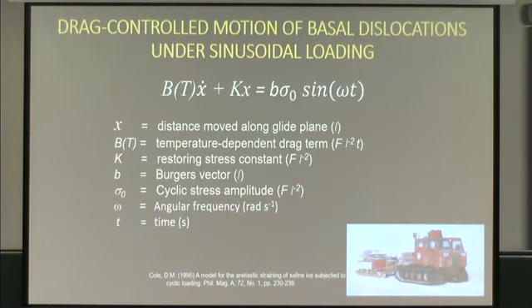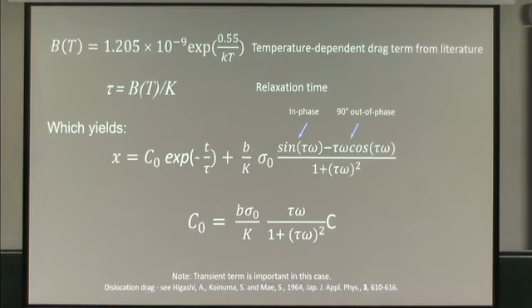So here's the physical basis for the model. You have a dislocation that's sitting at position X. Its response to a cyclic load is drag controlled. In other words, there's a temperature dependent drag that inhibits it as a function of its velocity. And there's also a microstructural stress that is acting on it as a function of its position. Physical quantities described here, nothing arbitrary at all. So one solves that. This is probably really easy for everybody locally here.